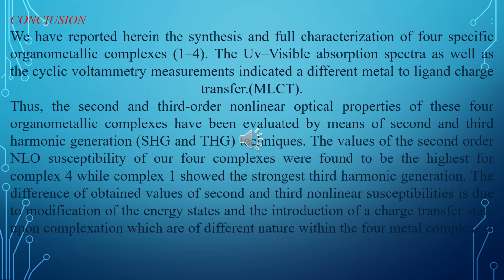The values of the second order susceptibility of our 4 complexes were found to be the highest for complex 4, while complex 1 showed the strongest third harmonic generation. The difference of obtained values of second and third non-linear susceptibilities is due to modification of the energy states and the introduction of a charge transfer state upon complexation, which are of a different nature with the 4 metal complexes.